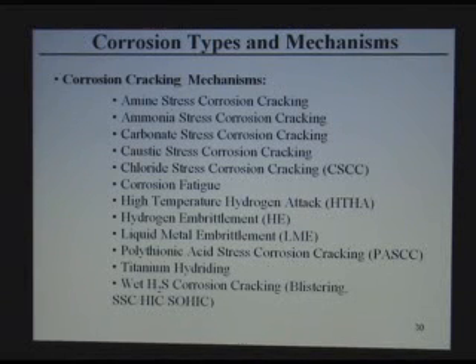Titanium also, if you have a hydrogen environment due to corrosion, hydrogen diffuses into the titanium and causes a lot of embrittlement. Wet H2S cracking is one of the mechanisms I mentioned here. They have wet H2S corrosion, which can cause blistering, sulfide stress cracking, hydrogen-induced cracking, and stress-oriented hydrogen-induced cracking.